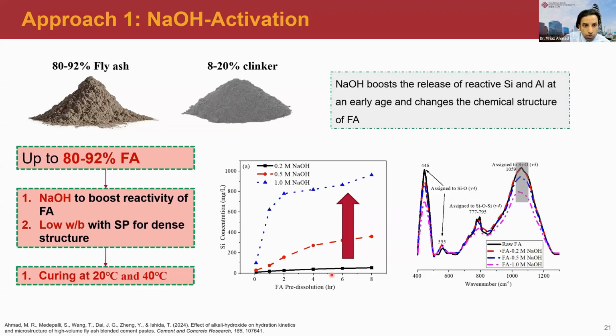If you can see, there is a huge boost or increase in the silica and alumina released. Normally at normal temperatures, if we don't use sodium hydroxide, there will be very little alumina or silica to react. But if we use some amount of sodium hydroxide, it can help to release a lot of reactive alumina and silica, which can react with the cement and improve the properties of the cement, which is very crucial for ultra low clinker cement. Besides that, it can also increase the early strength.